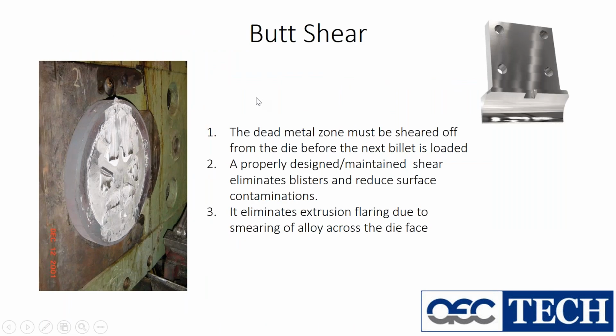Let's talk about butt shear. The dead metal zone must be sheared off from the die before the next billet is loaded in. Properly designed and maintained shear eliminates blisters, reduces surface contaminations, and eliminates flaring due to smearing that gets caught across the die, like you can see in here. This will contribute to container tilt, which will contribute to flashing, which will contribute to unscheduled downtime and productivity issues.